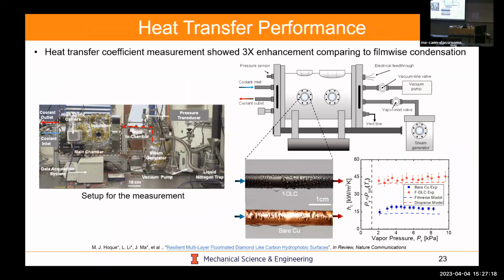What we do is test in a custom developed chamber that we have in lab. This is basically a pressure vessel where we could actually inject clean steam, get rid of non-condensables, and then mount tube samples to actually measure condensation heat transfer coefficient. And I saw this morning Solomon has a very similar setup in his lab. So I'm glad to see that he's working on good stuff as well. And so you could see that for a DLC coated tube versus a bare copper, you do get a heat transfer coefficient increase as expected, and it's stable over a range of different vapor pressures. The behavior makes sense as well with dropwise condensation.